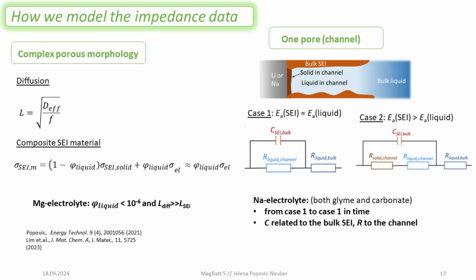One is when we have very similar activation energy to the liquid, and then we will have basically simply the resistance of the bulk of the liquid in series with the resistance of the liquid in the channel and the capacitance of the bulk. And then it gets a little bit complicated if we have the activation energy that is a little bit higher than the liquid but lower than the solid, right?